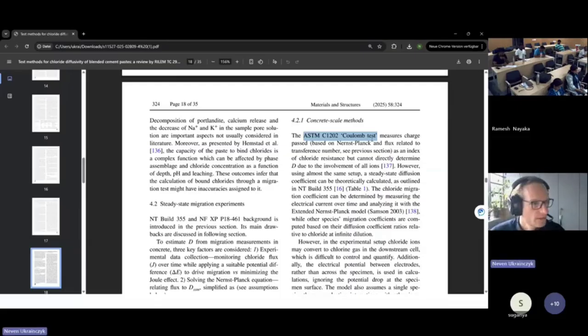The Coulomb test, so you are basically measuring just the charge passed as an index of chloride resistance, but you cannot directly determine the diffusion coefficient due to the involvement of all ions. However, using almost the same setup, a steady-state diffusion coefficient can be theoretically calculated, as outlined in NT Build. I think it's not so difficult to use a similar setup and switch to NT Build. I would recommend you to use the NT Build method.